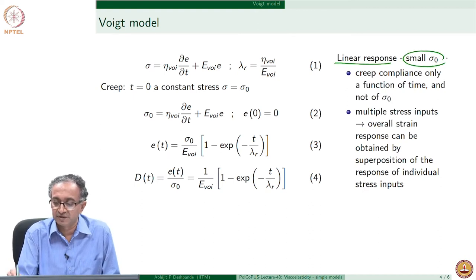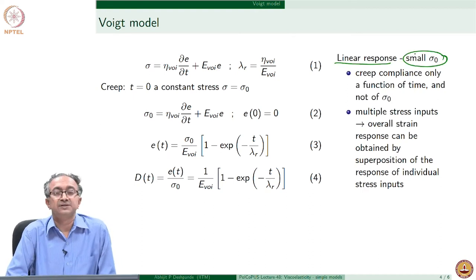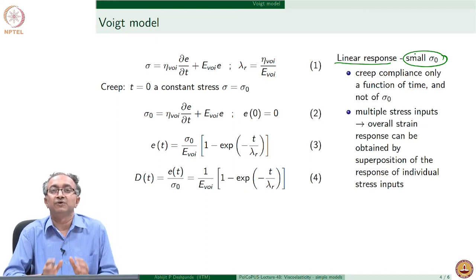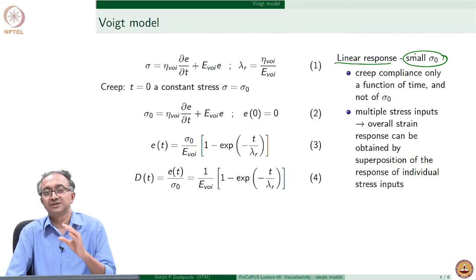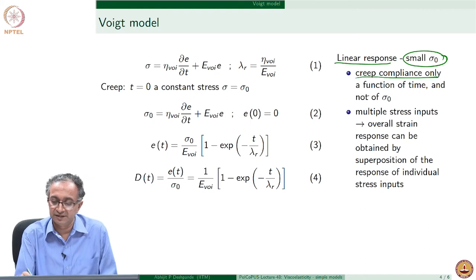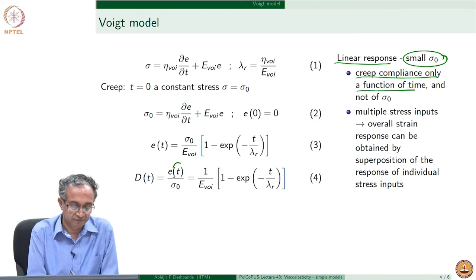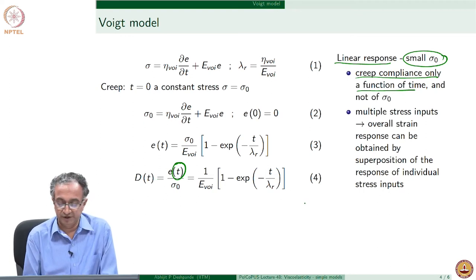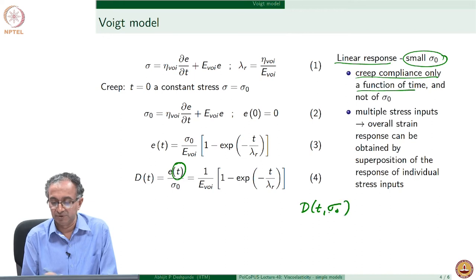Linear response means this analysis is valid only for small amounts of applied stress, so the equilibrium structure of the material is maintained. Due to this linearity, the creep compliance is only a function of time. In the case of a nonlinear response, creep compliance would be a function of both time and the applied load.